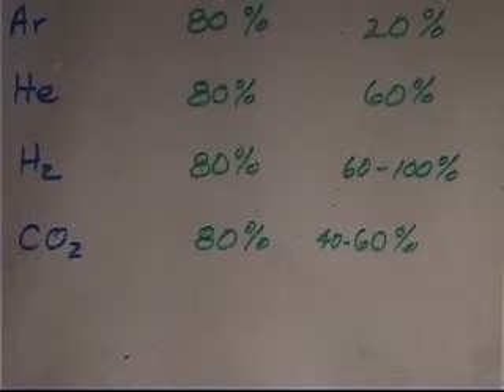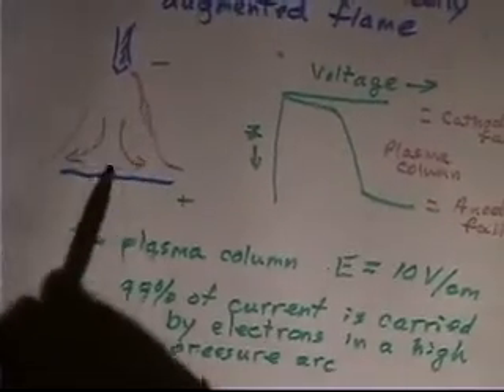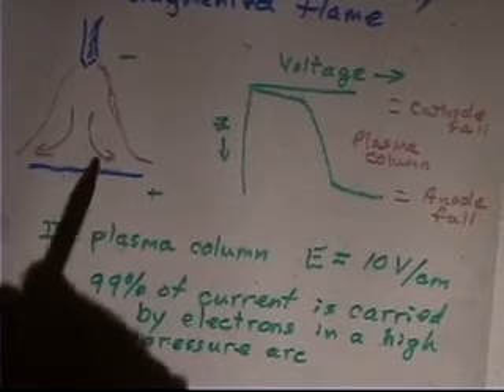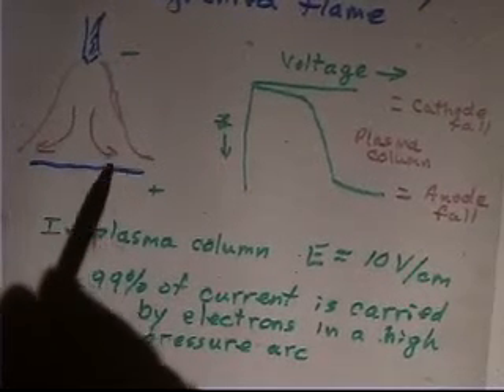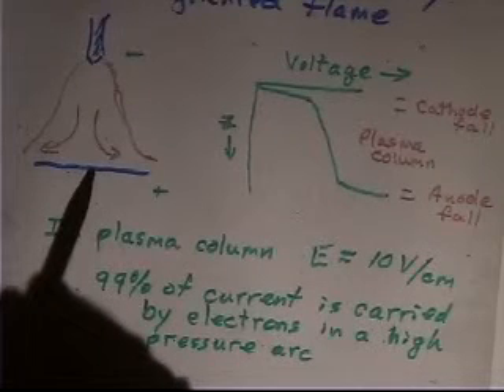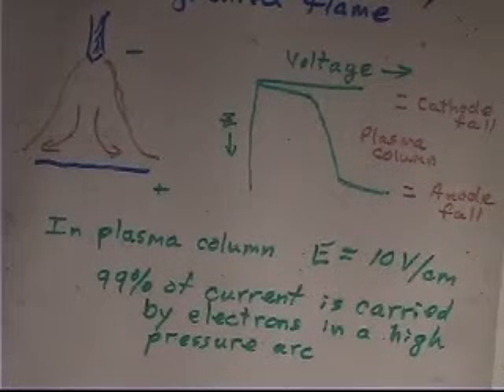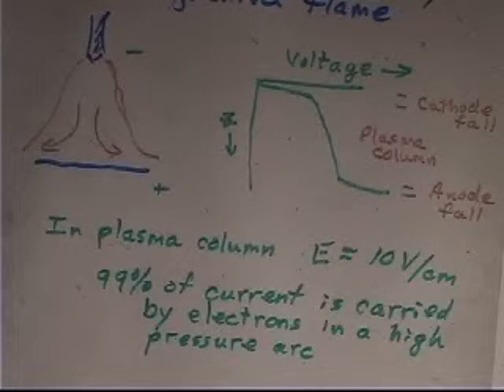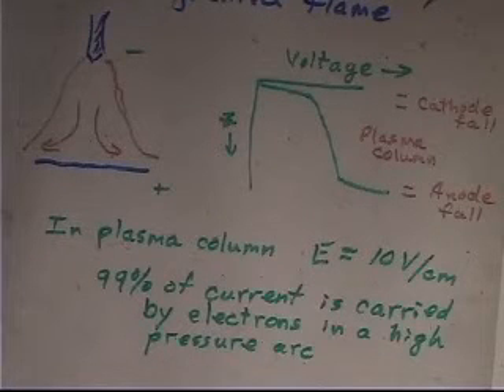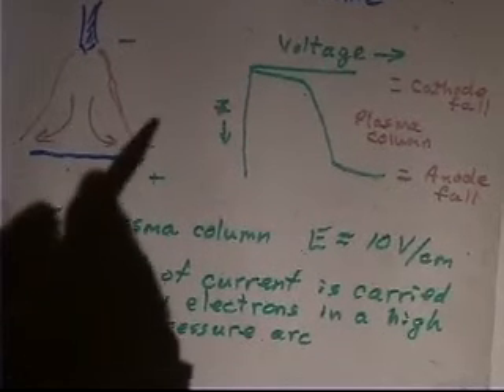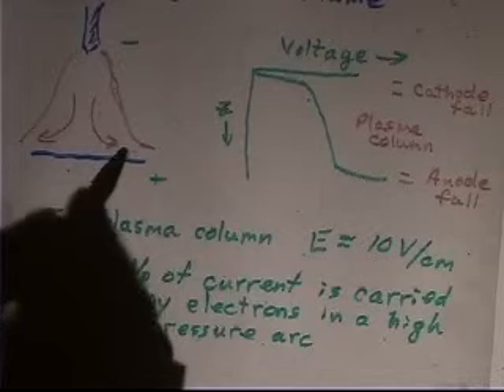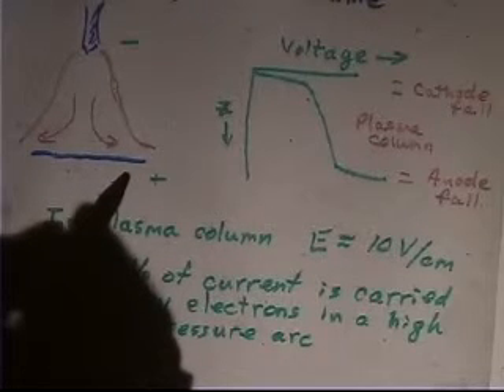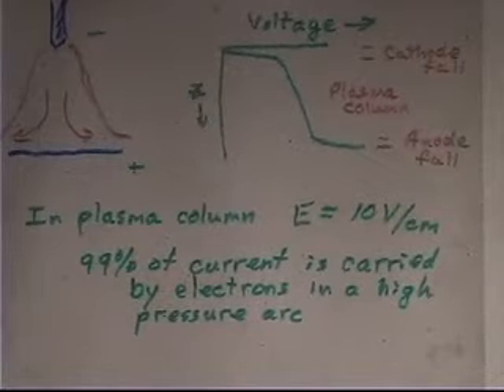When I do that, I have to put energy in to break the bond. But when it hits the surface of the weld where everything's cooler, so up here, I put energy into breaking those bonds. Down here in the boundary layer where everything cools off, it recombines. The oxygen and the CO recombine to CO2. The 2 hydrogens combine to H2. And when it does that, it gives up what we call the heat of recombination. The heat that was absorbed in dissociation is re-emitted down in the boundary layer as the heat of recombination. And that extra heat gives a hotter boundary layer, and gets transferred into the workpiece. In plasma physics, it's called the reactive thermal conductivity.